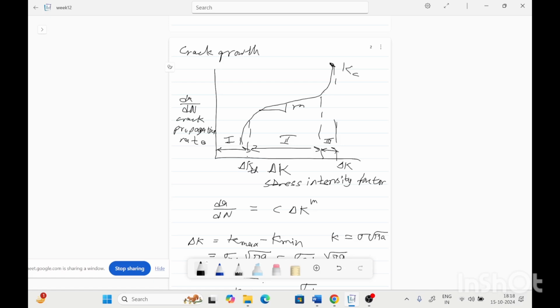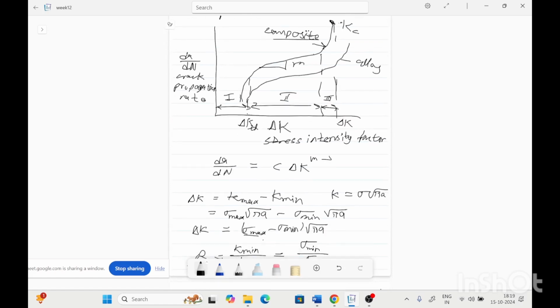If we consider this for a composite, then for the alloy the curve will be less steep. This type of curve we will get for the alloy, and this is for the composite. For the composite, the slope of this second region will be higher, meaning the m value will also be high for composites. So only the slope and the trend of the curve will change with the composite, but the regions will be the same.